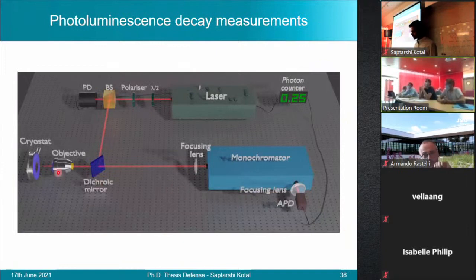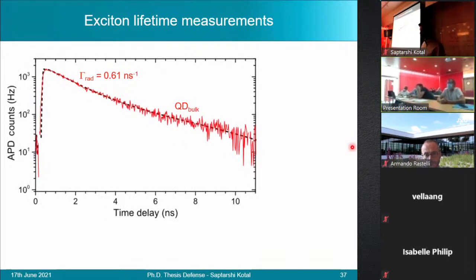Next, we detect the photoluminescence of our quantum dots, but this time we record it on an avalanche photodetector. And then we perform a time-resolved measurement by calculating the time intervals between the excitation laser pulse and the corresponding quantum dot emission on a photon counter. Such an experiment would produce a time-binned photon count spectrum as seen here. We see the trend which corresponds to an ensemble of quantum dots encapsulated in bulk. This decay curve is fitted with a biexponential function, which corresponds to the interconversion between the dark to bright and bright to dark excitonic states. And this is quite expected for quantum dots, for neutral excitons.